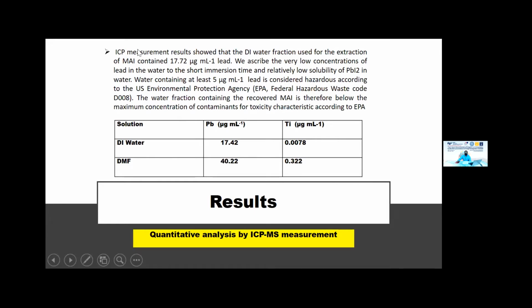After that, we used another detection method, ICP-MS. The ICP measurement result shows that the DI water contains 17.42 per milliliter, and the DMF solution 40.22. The concentration was low because we used only one cell. If we do many cells together, that can help. We can find more lead, and it is possible to recycle.